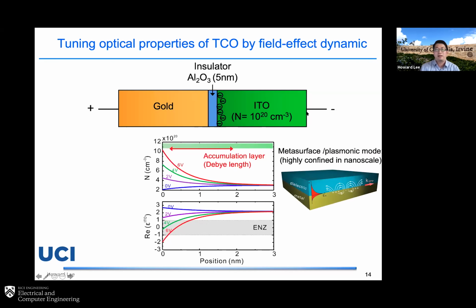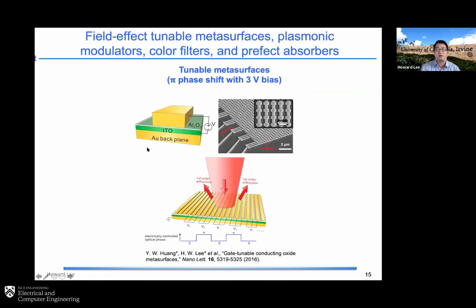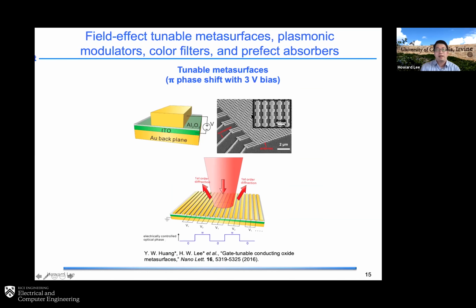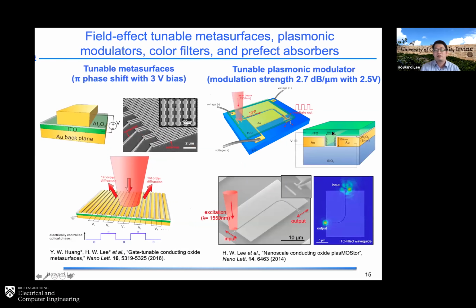That's why we have been making use of this field effect in TCO material to make a tunable metasurface before. For example, we integrate the ITO into a metallic structure, and by applying bias we were able to demonstrate a tunable phase shift of pi with quite a low voltage, which was published a couple of years ago. At the same time, we also demonstrated integrating this TCO material into a plasmonic waveguide structure to electrically tune it and make a plasmonic modulator. We have quite strong modulation strength of 2.7 dB per micron by applying less than 3 volts.